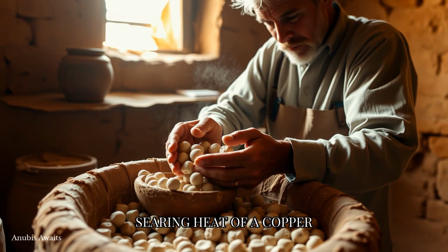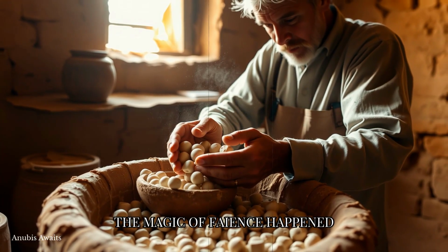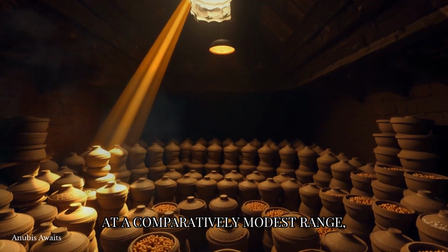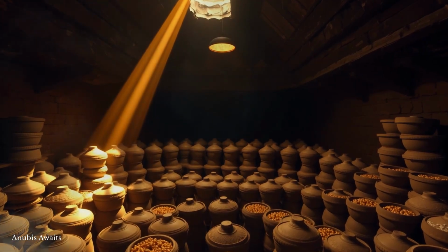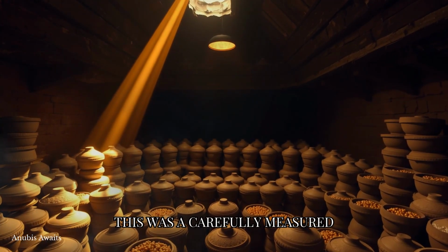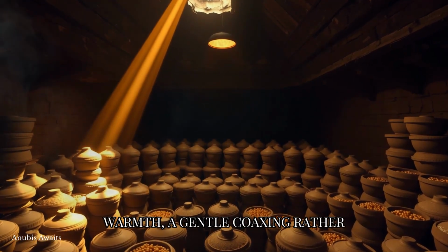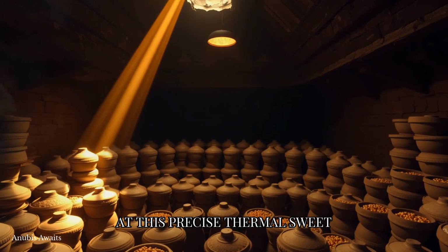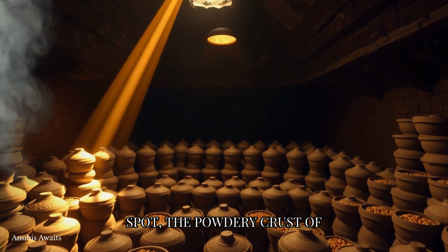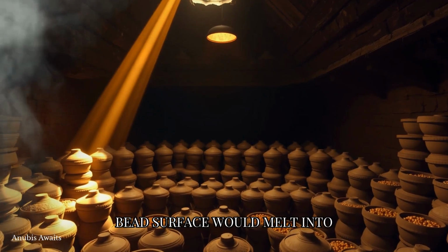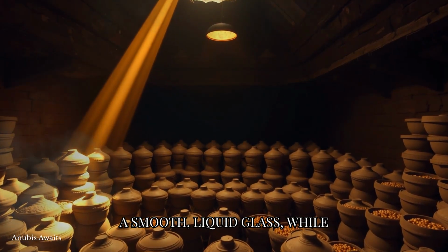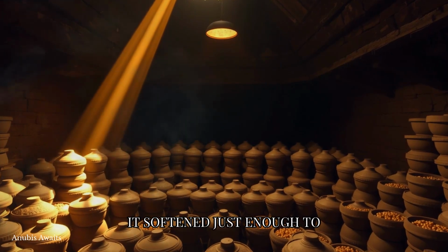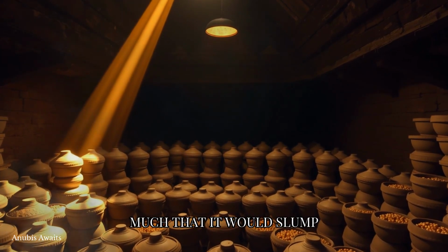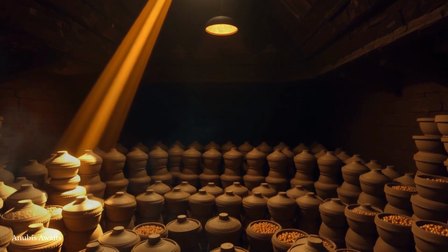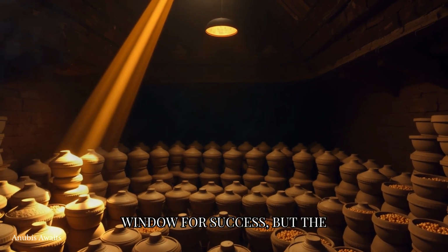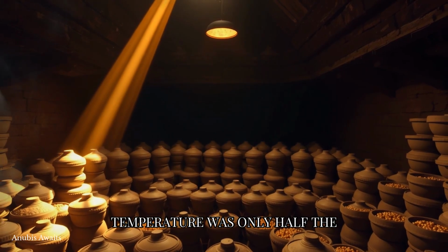It did not need the searing heat of a copper smelter. The magic of faience happened at a comparatively modest range, between 800 and 1,000 degrees Celsius. This was a carefully measured warmth, a gentle coaxing rather than a violent assault. At this precise thermal sweet spot, the powdery crust of salts and copper on the bead's surface would melt into a smooth, liquid glass, while the sandy quartz core beneath it softened just enough to fuse together, yet not so much that it would slump and lose its shape. It was a breathtakingly narrow window for success, but the temperature was only half the story.